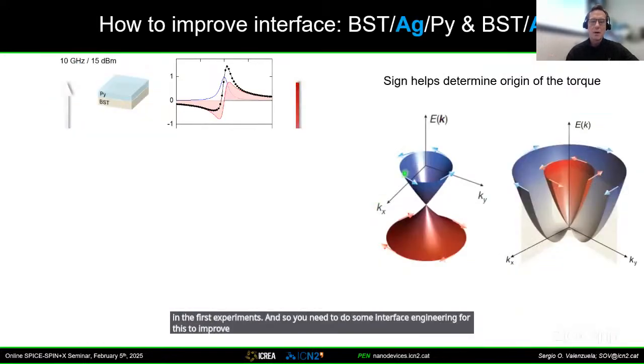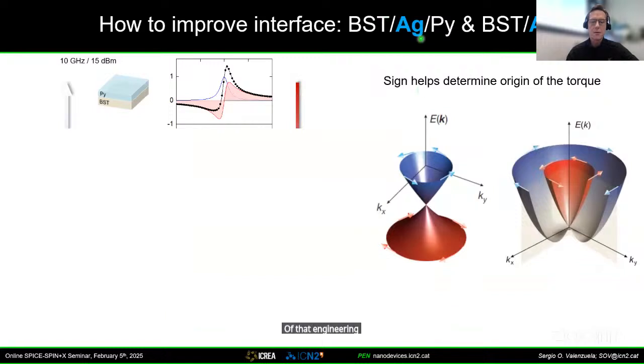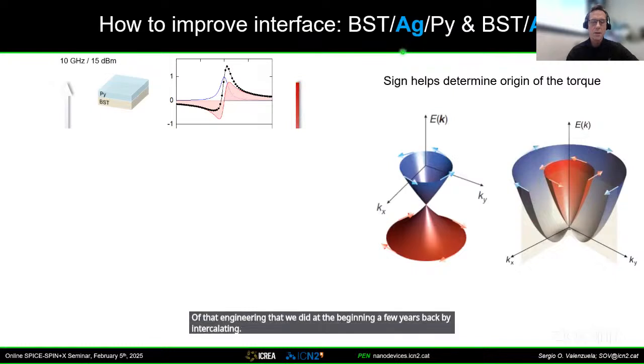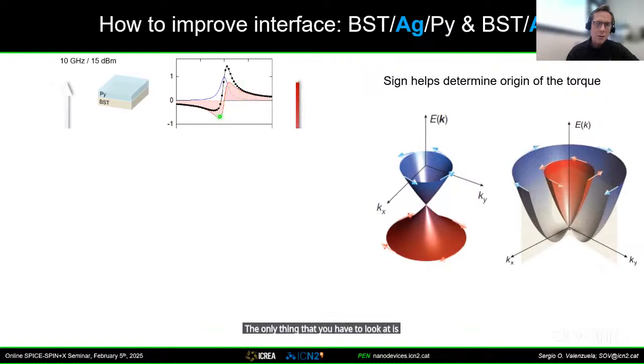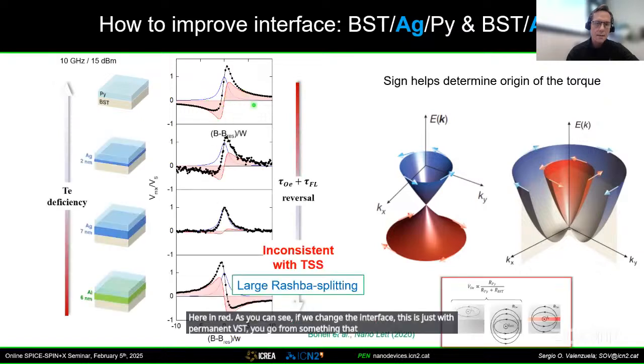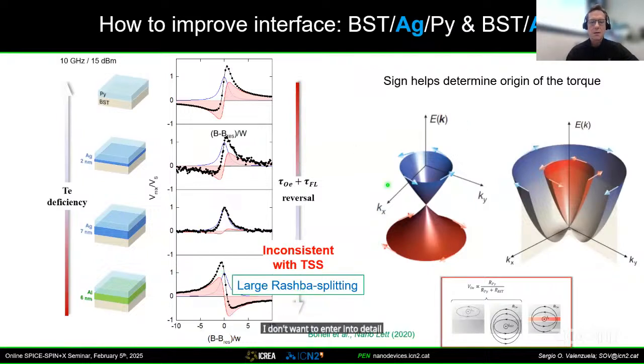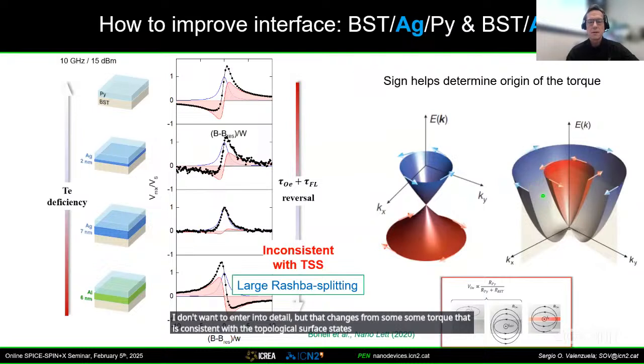And this is an example of that engineering that we did at the beginning a few years back by intercalating, for example, silver or aluminum. And here you can see the spin orbit torque in this system, in particular, by STFMR. The only thing that you have to look at is that the field-like torque is the anti-symmetric component here in red. As you can see, if we change the interface, this is just with permanent BST, you go from something that has this sign to something that has the opposite sign. I don't want to enter into detail, but that changes from some torque that is consistent with the topological surface states here with something that is consistent with Rashba-Edelstein effect, with Rashba splitting down here.